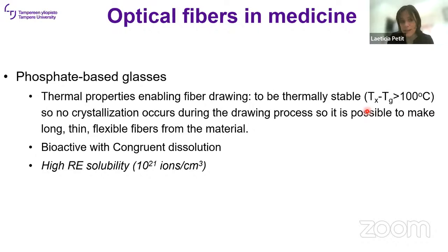You can change the glass composition for the glass to be bioactive. The phosphate glasses have this congruent dissolution, so they actually dissolve in the body layer by layer, so the composition of the glass actually doesn't change over time as compared to the borosilicate. And these phosphate glasses are well known to have this high rare earth solubility, so they are very good candidates for optical application.